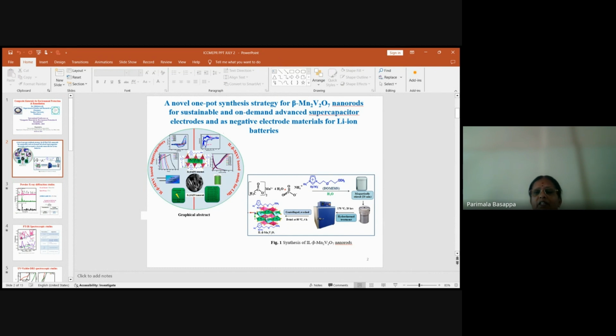The same experiment is repeated with ammonium manganese acetate and ammonium vanadate in a 1:1 ratio. 10 ml of this ionic liquid is taken with 40 ml of water, magnetically stirred for 20 minutes, and hydrothermally treated at 170 degrees for 20 hours. Again, centrifuged, dried, and washed. We got a brown precipitate of ionic liquid beta manganese vanadate.